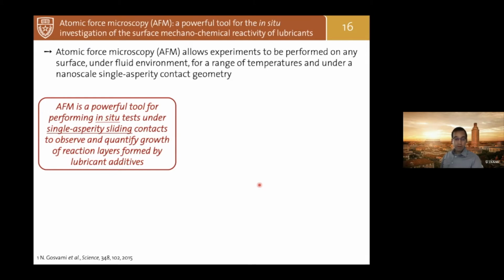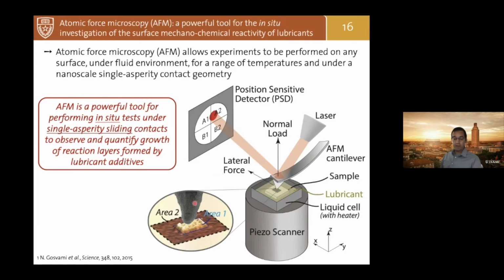Why? Because atomic force microscopy allows us to perform in situ tests in single asperity sliding contacts. For those of you who are not familiar with AFM, AFM uses a flexible cantilever, at the end of which you have a very sharp tip, and the two surfaces are pushed together, and you can achieve extremely high load and pressure in the presence of the ionic liquid. This allows us to understand and visualize what happens at the contact in real time, while knowing basically the shape of the tip, meaning we have an accurate measurement of the pressure.